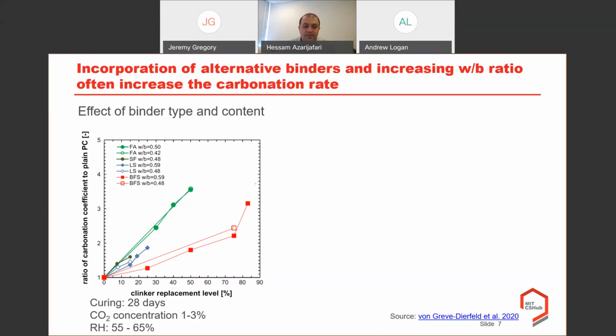What we can observe here is that once we are replacing with these alternative binder materials, the carbonation coefficient will increase and can be tripled compared to the plain Portland cement in the case of, for example, fly ash, once we are replacing 50% of the clinker with fly ash. The same case for blast furnace slag, that we can replace up to maybe 80% in different mixtures, and we can see that the carbonation can be increased up to 3 times that of the plain Portland cement. So this is one effect. The alternative binder increase in the mixture will increase the carbonation coefficient compared to the plain concrete.